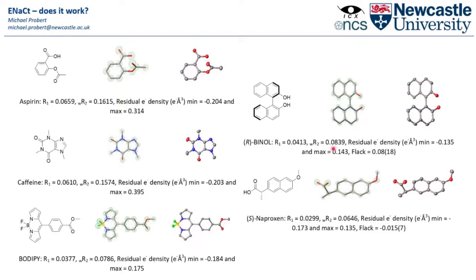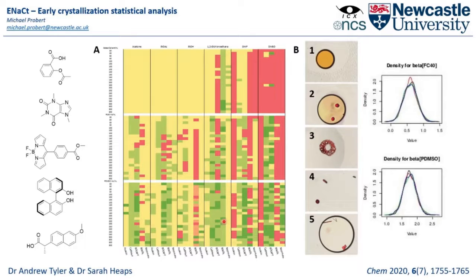But what we wanted to do with this set of compounds was look at whether or not our approach was making things better. So we applied a bit of statistical regression to these systems. So we took our 5 test cases, we tried them with different solvents and then different oil encapsulations. So this top row here has no oil in encapsulation at all, and then we have 2 different types of oil on the bottom 2 larger rows. And then within each one of these solvent systems we have our 5 different compounds, our analytes, and then essentially the way to interpret this image is the more green, the more successful the crystallization was.